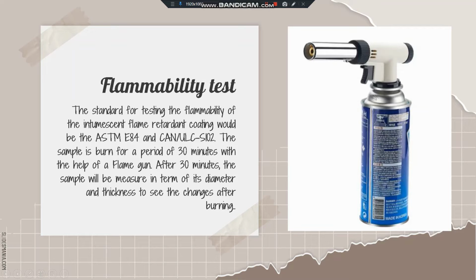Flammability test. The standard for testing the flammability of the intumescent flame retardant coating would be the ASTM E84, or American Standard for Testing and Materials, and the other standard is CAN/ULC S102. The sample is burned for a period of 30 minutes with the help of a flame gun. After 30 minutes, the sample will be measured in terms of its diameter and thickness to see the change after burning.